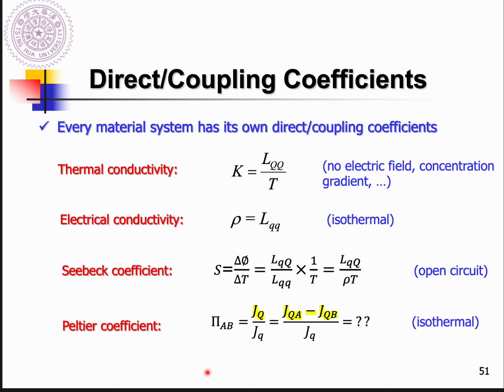Okay? Next. We finished the Seebeck coefficient and also told you that the Seebeck coefficient equals the coupling coefficient divided by rho T. And in order to measure the Seebeck coefficient accurately, you need to connect to the voltmeter under the open circuit condition. So then you can measure the accurate Seebeck coefficient.